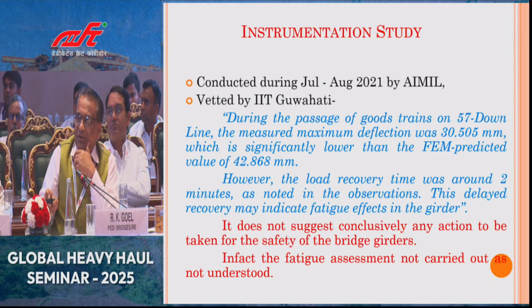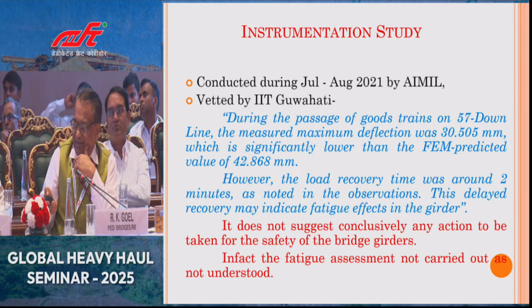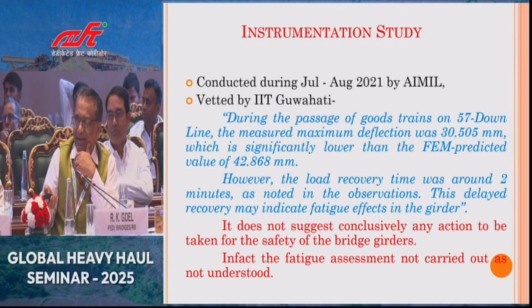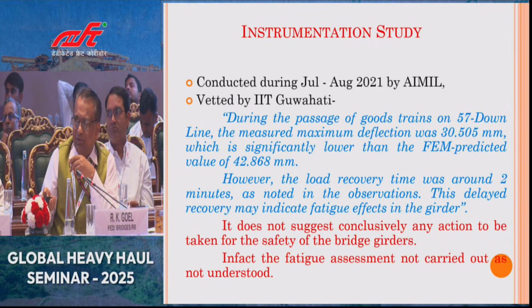This bridge was also instrumented by Messrs. AIMIL, and IIT Guwahati has examined their report. So there were deflections observed of the order of 30 mm, whereas they could have been 42 mm. So that less deflection was probably due to, again, redundancies in the structural arrangement. And finally, they said something about the fatigue, but they had not actually done the fatigue analysis of this bridge. So their report was not actually drawing any conclusion.